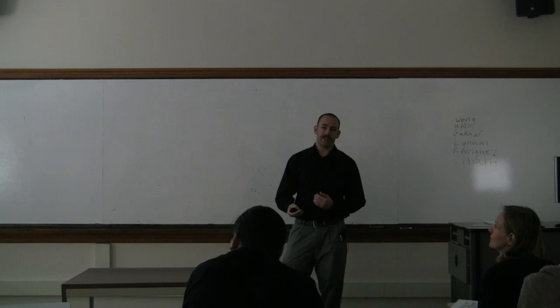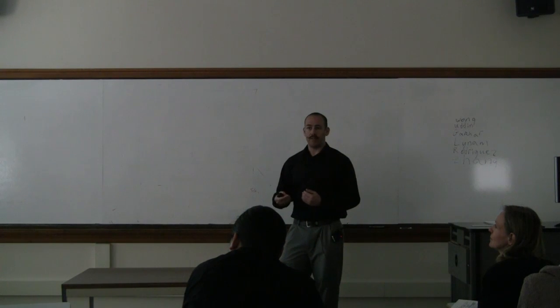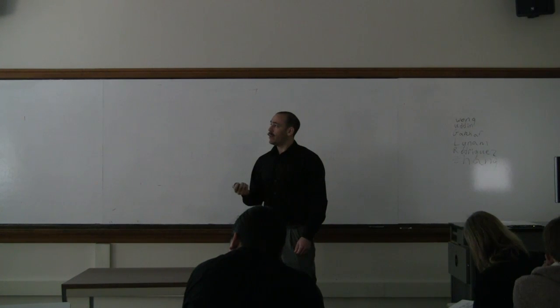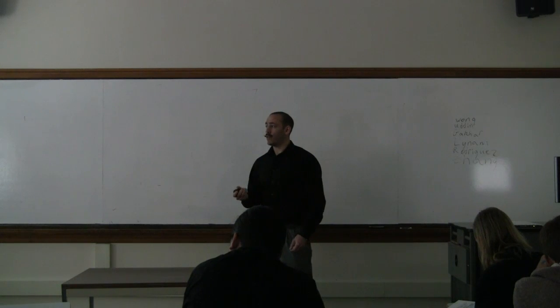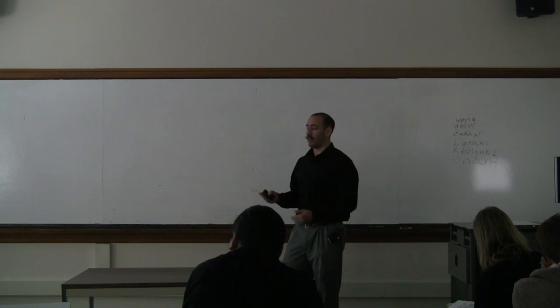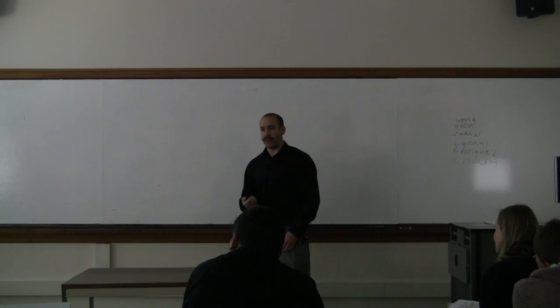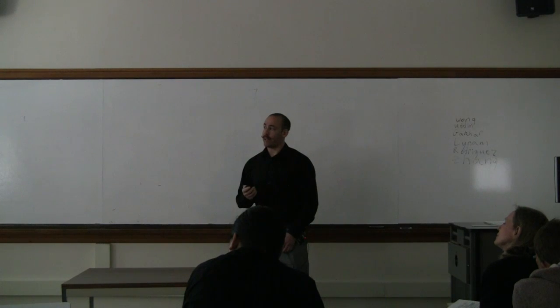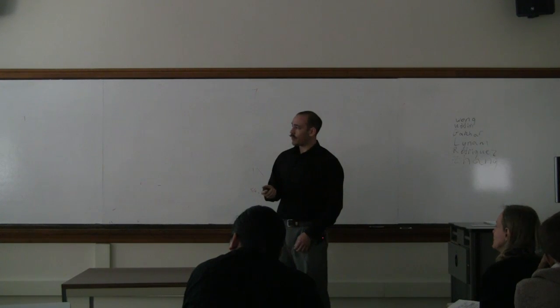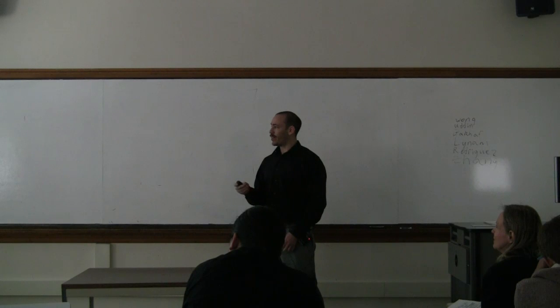Okay, here's a typical open circuit potential. For all samples, once the salt solution was added, it would stabilize around 20 to 120 seconds. This one stabilized at about 25 seconds. And here we have a polarization curve for the optimal formulation that I had found. There were others that had slightly better corrosion parameters based on the data acquisition software that we had, but these formulations had low adherence, and will be shown in a later section with SEM imaging as to why we did not choose this sample. This one has an I-corr of about 0.3 actually, average for these three samples.